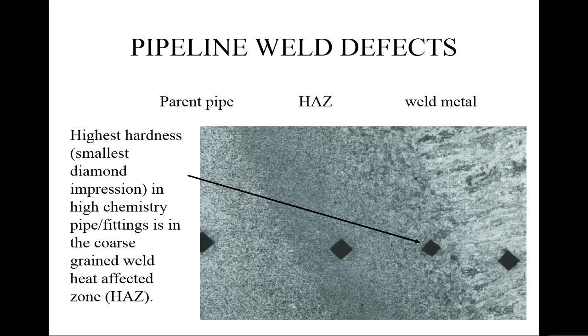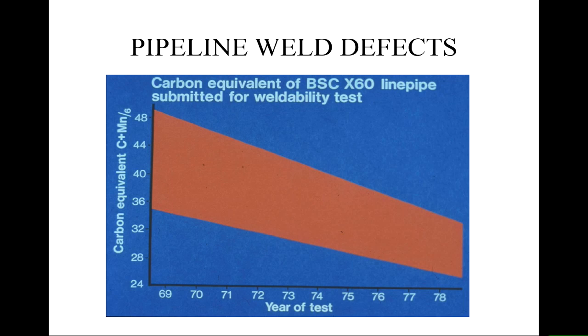And we can do this local mechanical test with a hardness impression that will give us an indication of what's going on. And you can even polish the surface of a weld and use a portable hardness tester to actually monitor the heat affected zone hardness if you really need to. So what do we want to be able to do to get a good material for welding?